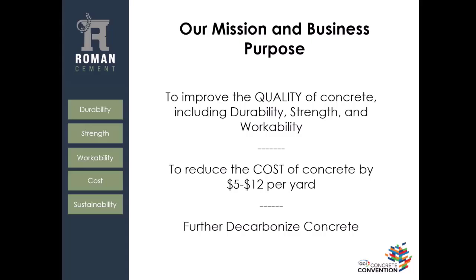We started off with the technology at particle size, select a ternary blended cement, and in our ideal cement we would have, in a broad distribution of particles, cement within a certain zone. We would have a very ultrafine pozzolanic material that's very reactive, and a coarse mineral filler, in a particle size distribution. What we did with concrete was just use materials that we could find off the shelf, that we didn't have to specially process, so we could just implement this at the concrete level.